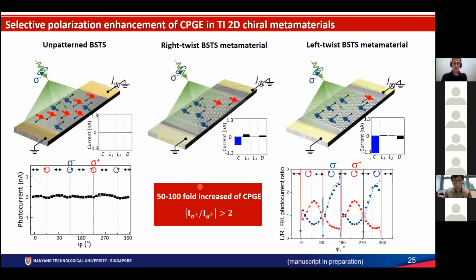So first of all, we observe a much higher increase of the CPGE. We go this time from between 50 and 100. And what we observe then is that you can suppress by twofold, well, let me call it the unwanted chirality in the sample. So effectively, you identified a way to control the topological response, the electronic topological response, in the material.